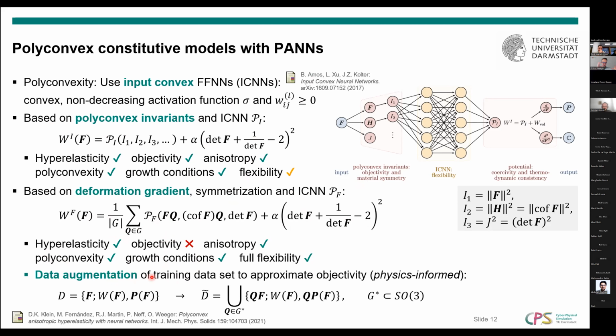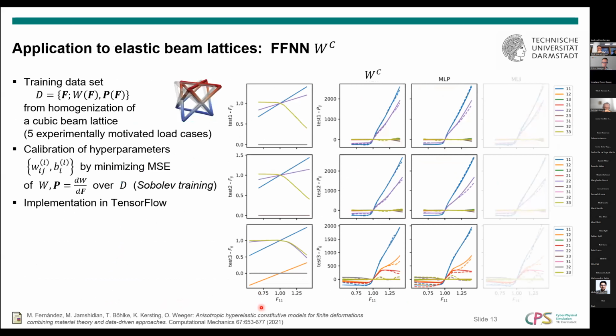So basically we have our data set, which we use for the training, which contains deformation gradients and the corresponding strain energies and stresses. And now we use certain rotations. Ideally, we would have to use all infinite rotations that are in the group SO(3), but we can only use a finite number. And basically, we rotate all the data with these rotations and enhance our data set. And then we hope by showing the model these additional inputs, it will learn the objectivity requirement by itself and approximate it in a more or less accurate way.